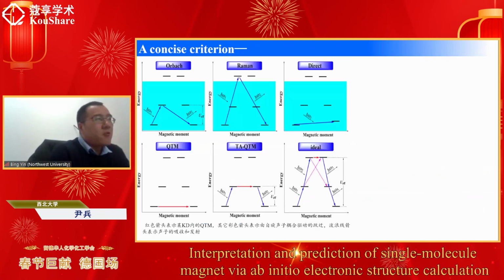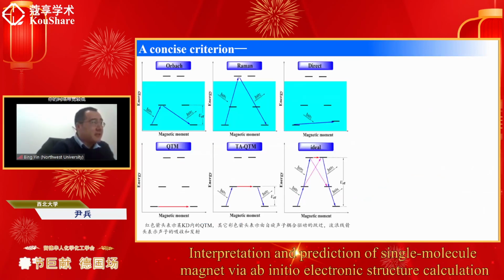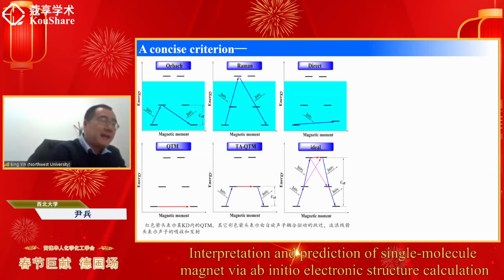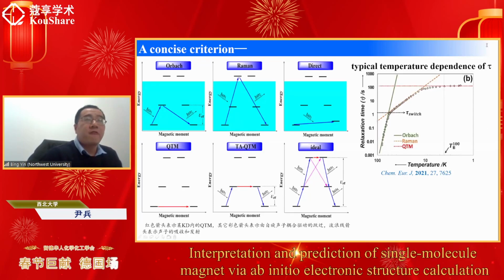There are several different pathways for the relaxation to proceed. The typical ones are listed in this figure, and it will increase the complexity of the study of single molecular magnets, because in principle, you need to consider all these relaxation pathways. But fortunately, the typical temperature dependence of relaxation time shows different dependence in different temperature regions. So in the high temperature region, the behavior is determined by the so-called Orbach pathway, and in the intermediate temperature region, the behavior is dominated by the so-called Raman relaxation pathway, and in the low temperature region, the behavior is dominated by the so-called quantum tunneling of magnetization, QTM, in the ground state. So maybe we could reduce the number of pathways which we need to consider to 3.